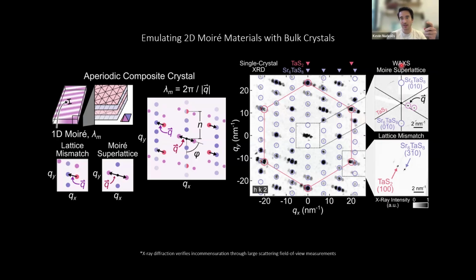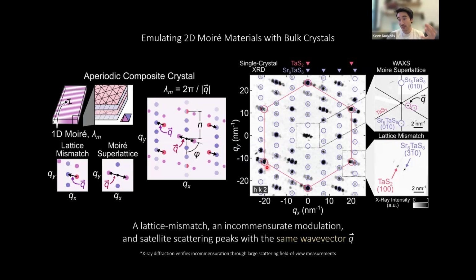So using this high resolution X-ray diffraction technique, we find that indeed the hexagonal and monoclinic layers are separated by a very small wave vector q, where that same q vector is emulated around the center for a long wavelength incommensurate modulation, as well as it explains all of these satellite peaks. And so this is really great that the lattice mismatch, the incommensurate modulation, and all of these satellite peaks are explained by exactly the same wave vector q. They all have this one q vector that appears everywhere.